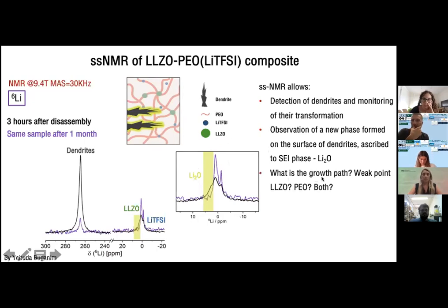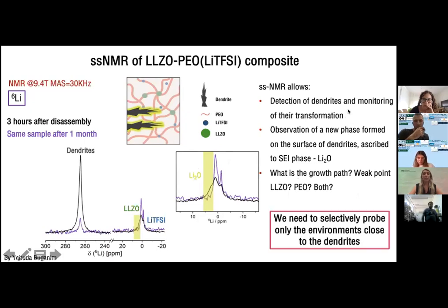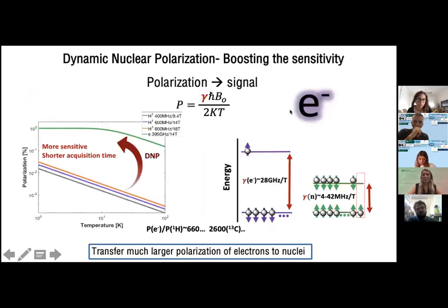However, we still have no information about the growth path of this dendrite. What is the weak point in our composite, LLZO, PEO, or the interface between them? So we need to somehow selectively probe only the environments that are close to the dendrite and not the whole picture, as we can see here in solid state NMR. So how can we do that? We will use dynamic nuclear polarization.